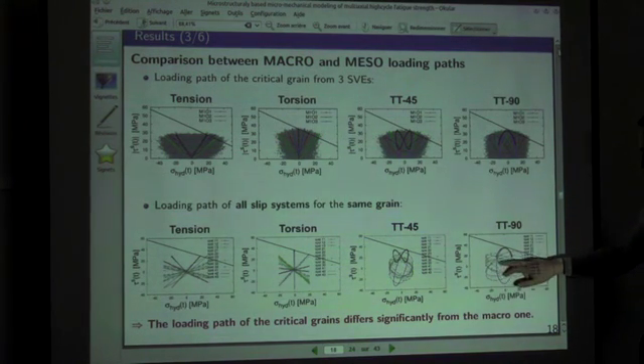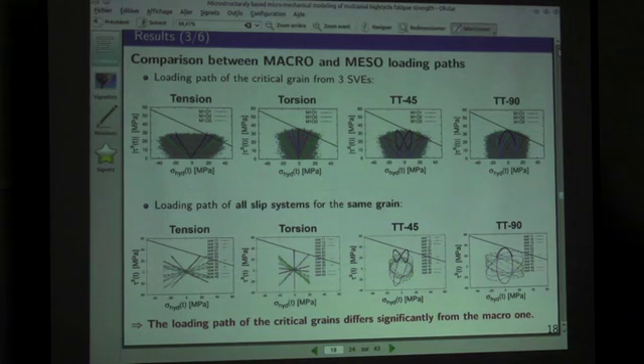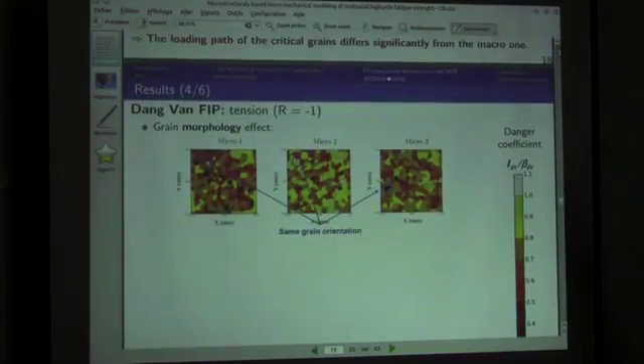And what you can see here is that you can fit, of course, some micro response here, for example, on this grain, with this loading path. But here you have some other slip systems in the same grain that experience loading paths which are very different, but as critical. So what tells us that it's going to be this one or this one that's going to initiate at the end? So such analysis can give us some information about the variety of the loading paths that we have at the micro scale, and I believe it's quite interesting for interpretation.